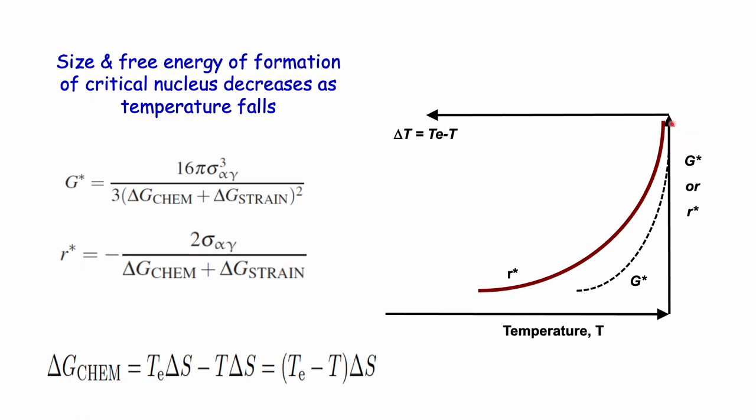Anyway, so here, we use this figure to try to reinforce this. When you change the temperature for processing, this is the temperature with the value linked with the TE. So lower temperature, you will get a decreased G star. And also you will get a smaller value for R star as well. So the physics here we try to explain is the G star value is linked with the driver force delta T, linked with the supercooling value. Lower temperature, the barrier for the transition getting smaller. Then lower the temperature for processing, you also find the thermally stabilized particle, minimum particle size, R star, also getting decreased.